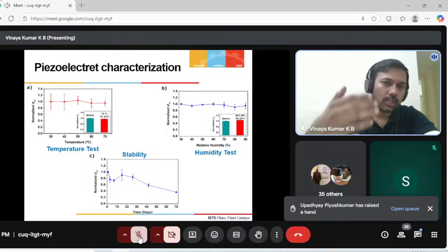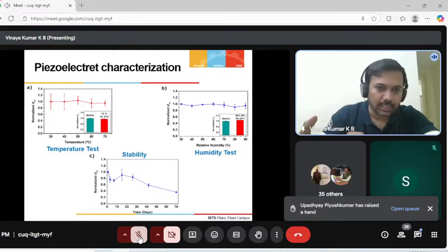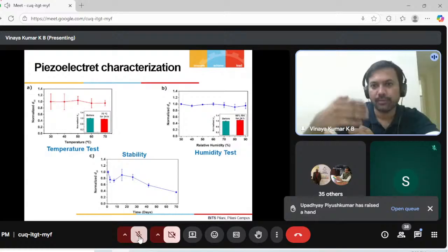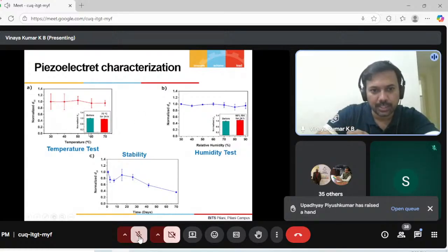So we also wanted to know the stability of these sensors depending on the different temperature and different humidity. As you can see, the temperature is going from like 30 to 70 degree. The sensor response is quite repeatable with a change of 20%, and then at humidity not much variation.